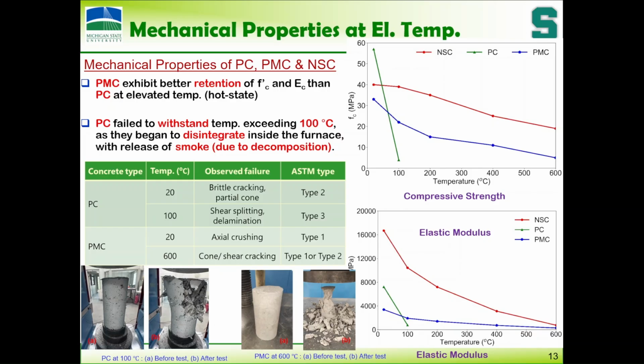Look at here: normal strength concrete, the red line. This is how strength drops with temperature. These are all tests done in the lab. Now, if it is polymer concrete, can you see here that at 100 degrees itself it drops? Maybe it's a little bit here and then there's a jump, but overall, once the Tg is crossed, it drops very highly.